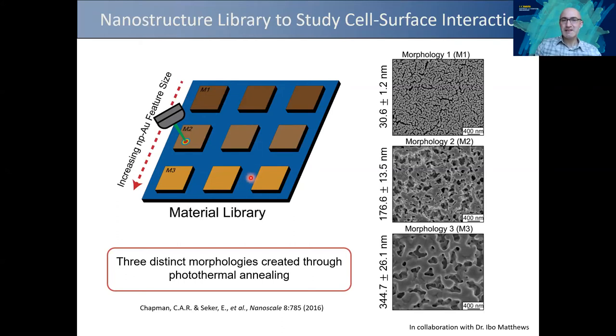So what we've seen here is that if you have these really fine morphologies, nothing sticks, neither neurons nor astrocytes. And this is actually well known from the focal adhesion studies, where if you are below a certain focal adhesion radius, cells cannot stabilize themselves. If you go to a little bit larger morphologies, neurons tend to stick better and astrocytes cannot. If you go to much coarser morphologies, it begins to approximate a planar surface and the effect is lost. So it's really in the sweet spot of about 100 nanometers where we are seeing this effect. And that's what we tune our electrodes to.